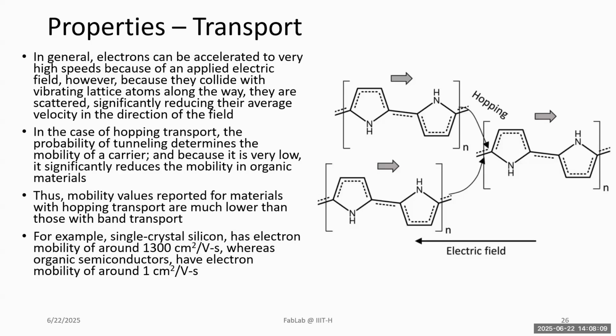So in general, electrons can be accelerated to very high speeds, but because of the fact that they are scattering at these junctions, or you could say at these barriers, their average velocity is reducing, and you will get lower mobilities. If you're getting single crystal silicon mobilities of 1300, in organics you will get mobilities of around 1. So it's a 1000x difference because of this problem.